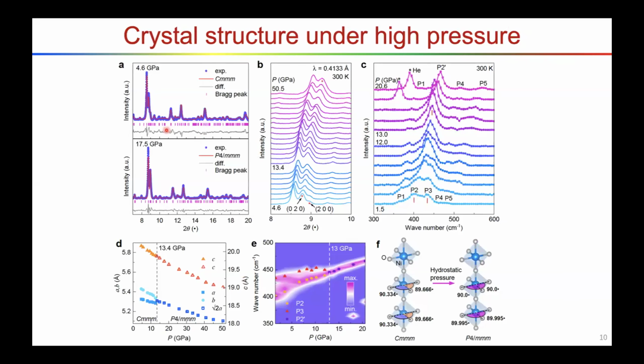We also measure the structure under high pressure. Here's the measurement by synchrotron X-ray diffraction, and under high pressure there's a structure transition. You can see here at low pressure the two peaks are separated, but as we increase the pressure, they merge together, indicating a structure transition. Here's the lattice constant, and the structure transition happens at 13 gigapascals. Okay, but the data quality is not very good, so we repeated the measurements by Raman scattering.